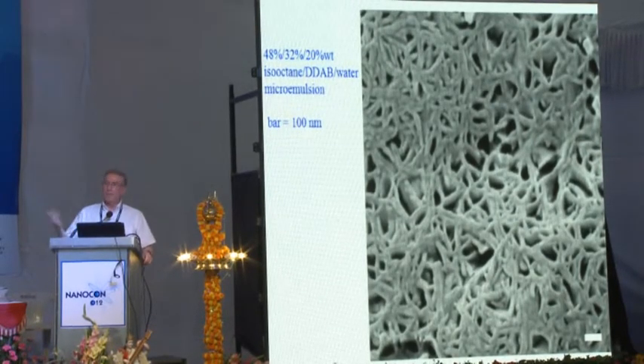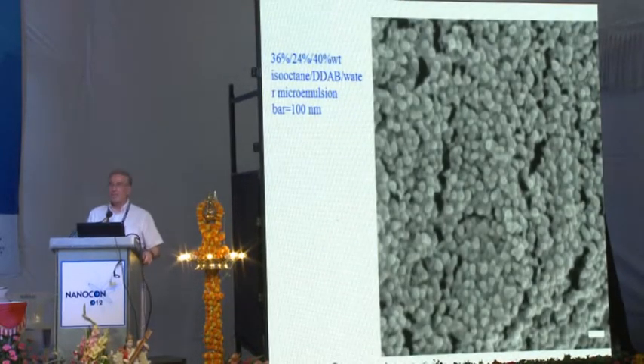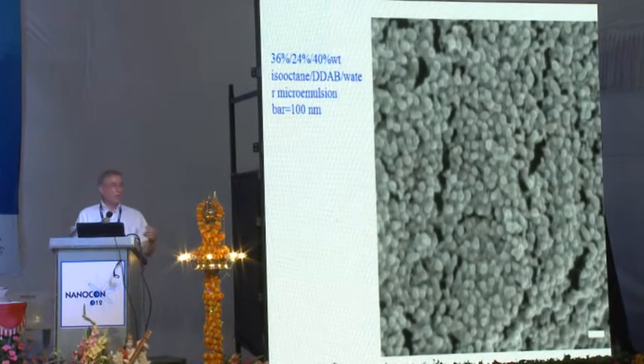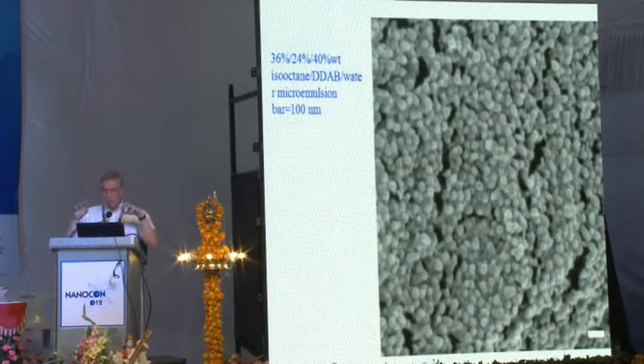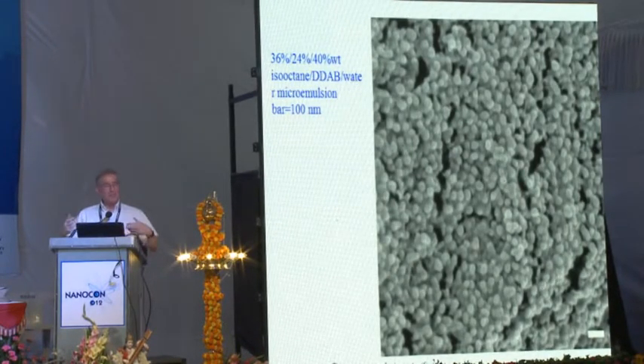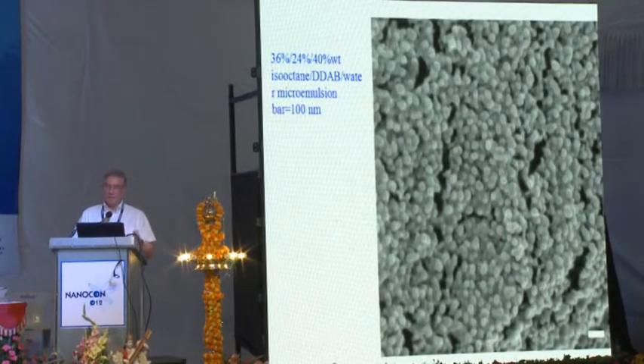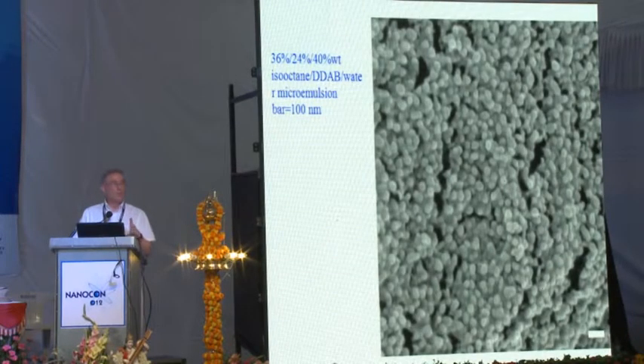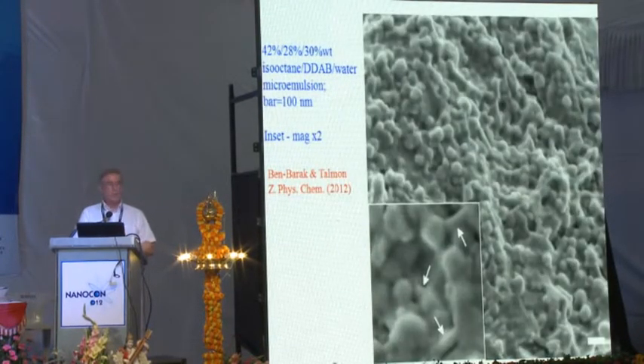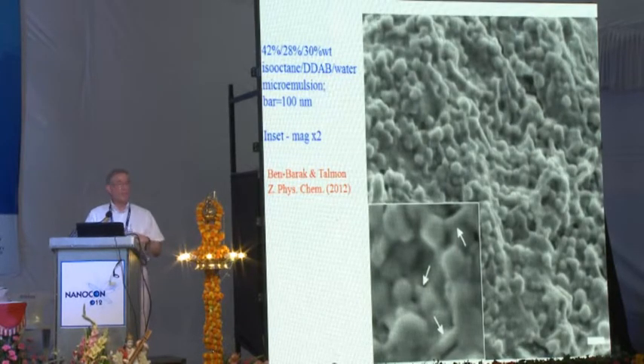But this is not enough. Now let's add some more water and see what happens. And this is what happens. As you can see here, the structure is completely different. You have oil, you have water droplets surrounded, I'm enthusiastic about it, water droplets surrounded by oil, and this is exactly it. Moreover, if you take an intermediate concentration of water, you get the intermediate structure, okay? On the lower left side, you see the transformation from water to oil.